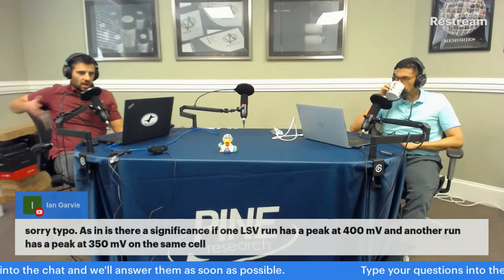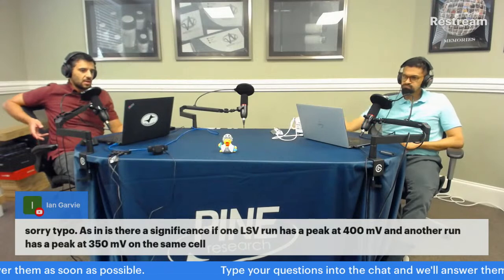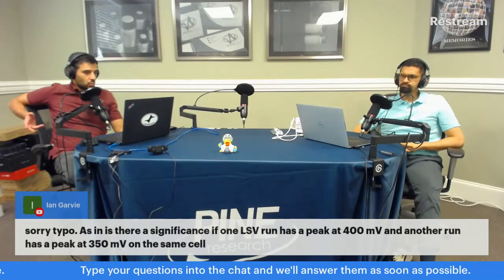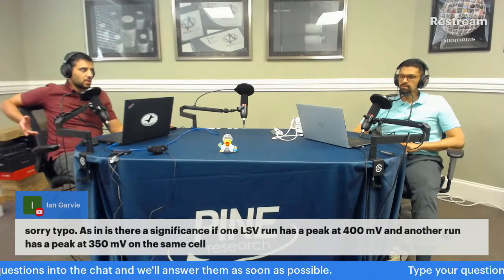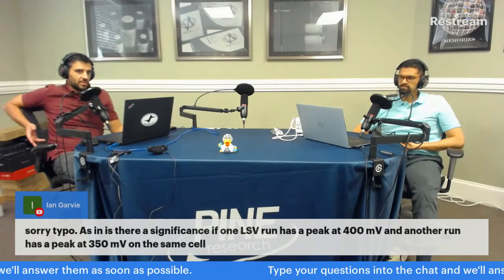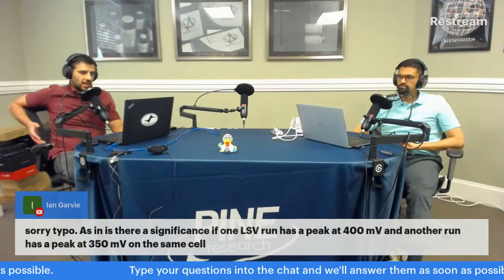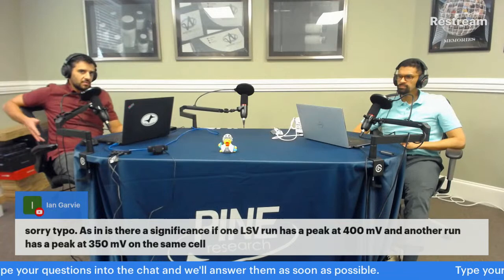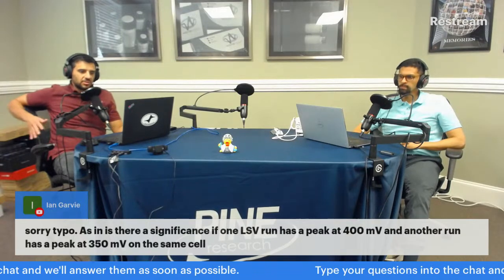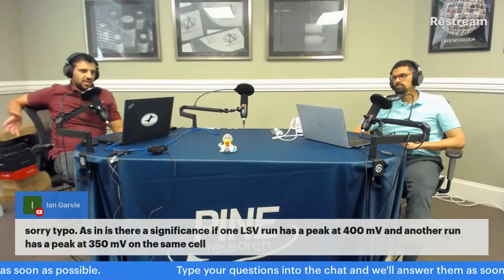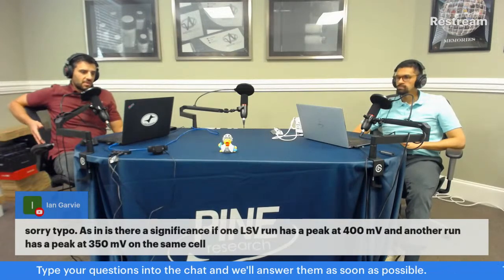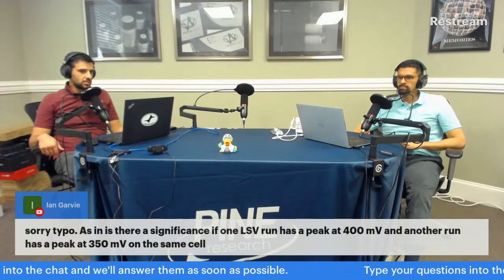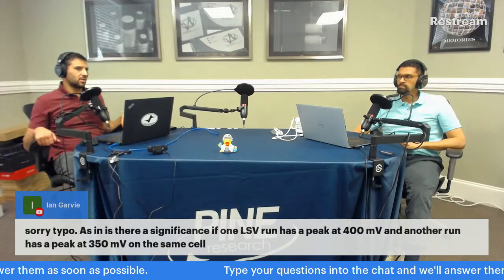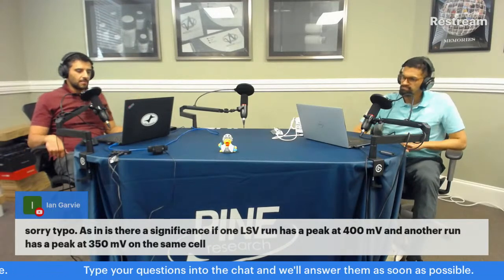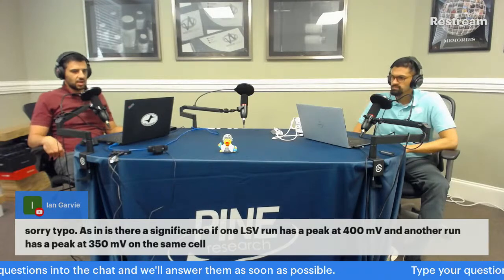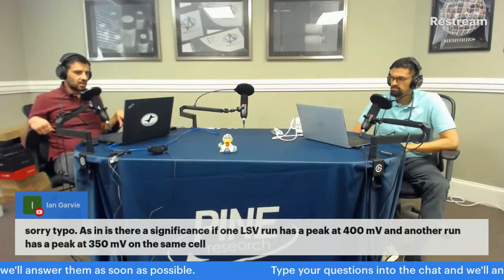In a vacuum, whatever situation you're looking at, is the peak position getting better or worse? Is the overpotential decreasing or increasing? If it's getting better over time, it means you're probably activating your catalyst in some way, the same way that you do multiple CVs before you start to clean the surface and get a fresh surface. That might be what's happening. Or it's the other way. If it's getting worse, your catalyst might be deactivating or something. Otherwise, there's just a lot of possibilities here because it's a fuel cell.